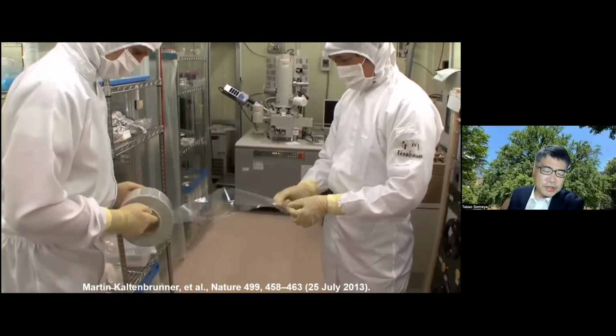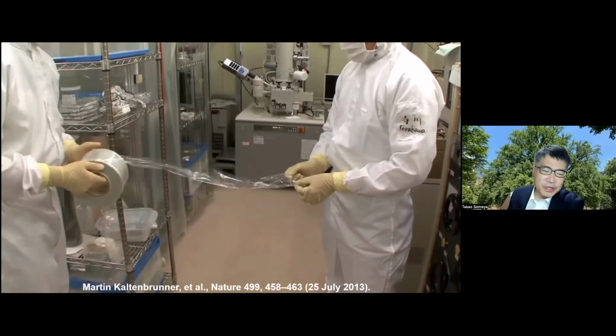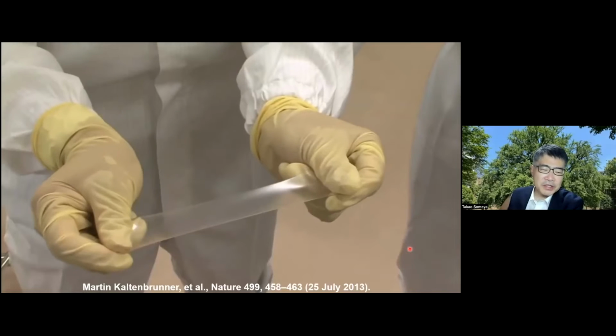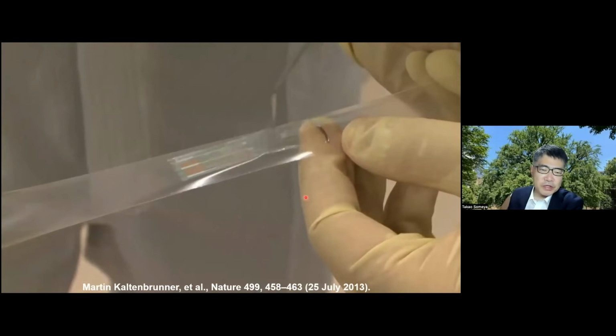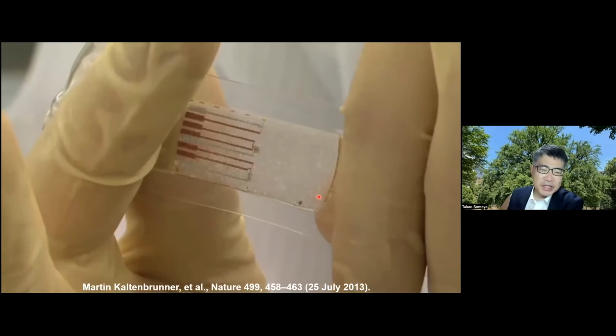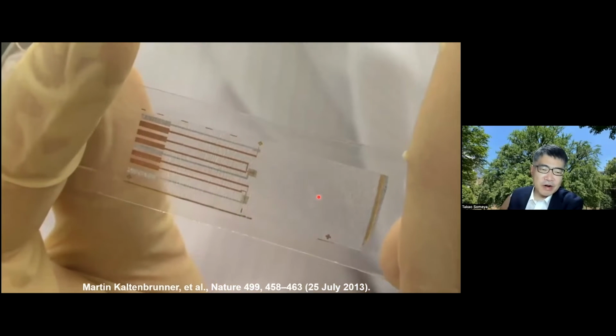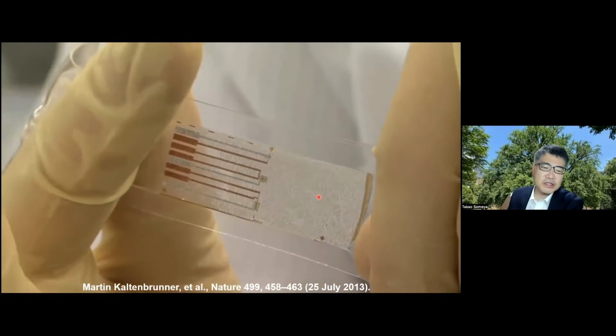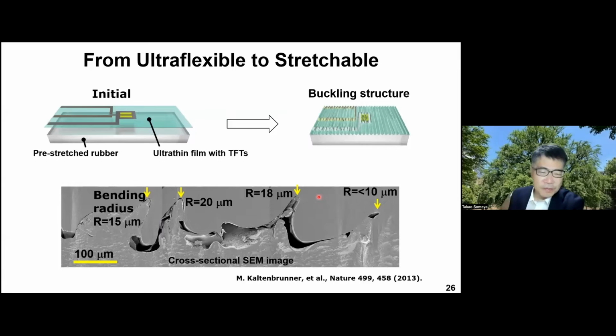And we used commercially available PET or PEN film with a thickness of 1 micron. After fabrication, we prepare the pre-stretched rubber and laminate our devices onto the rubber, utilizing the wrinkling structure. So the last step is quite important, and then I want to show you the fabrication process in detail.